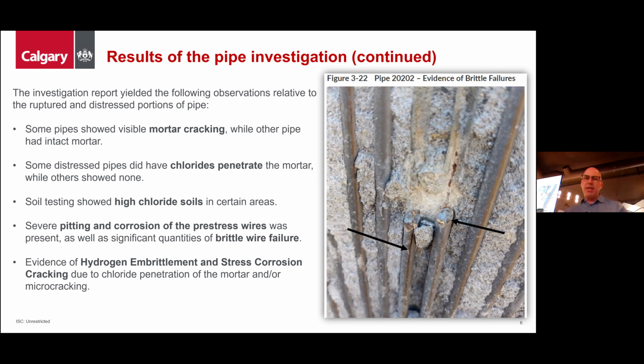Additionally, severe pitting and corrosion of the pre-stress wires was present in the pipe that had ruptured, as well as quantities of brittle wire failure. As well, there is evidence of hydrogen embrittlement and stress corrosion cracking in the pre-stressed wires in this particular piece of pipe, appearing to be due to chloride penetration of the mortar and the micro cracking. So that's where we do think that that is the primary cause of this particular piece of pipe failing.